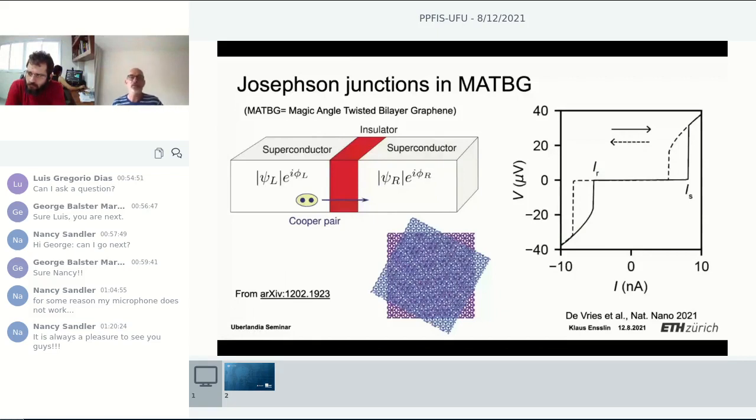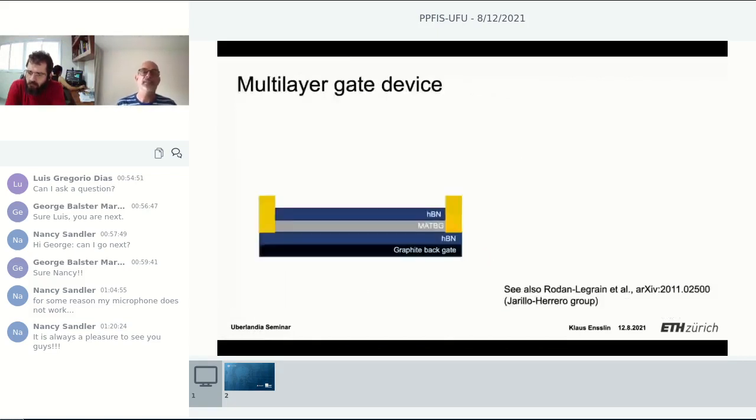So now you have our device. This is this magic angle twisted bilayer graphene embedded between hexagonal boron nitride, with a graphite back gate. We take two gold gates on top, we cover it with an insulator, have another gate on top. And now you see we can have basically